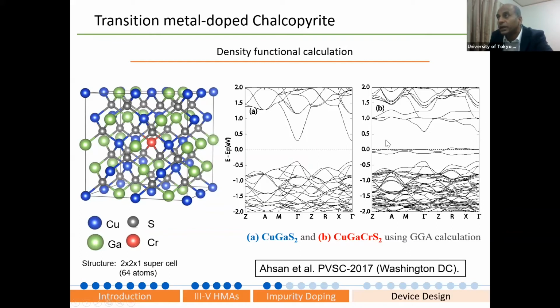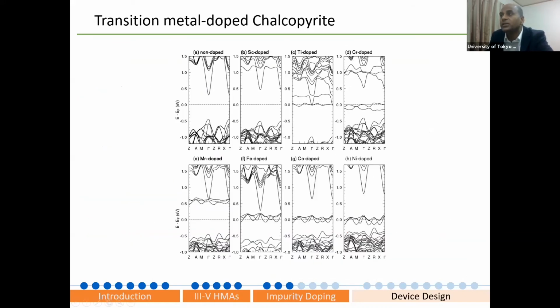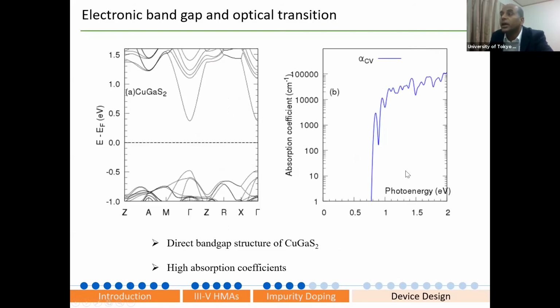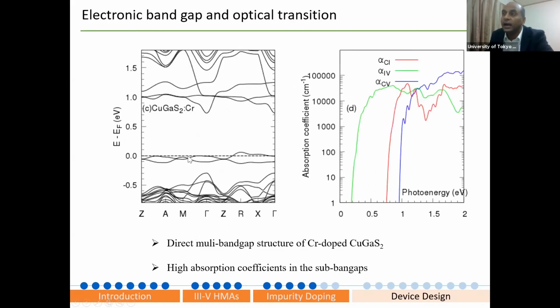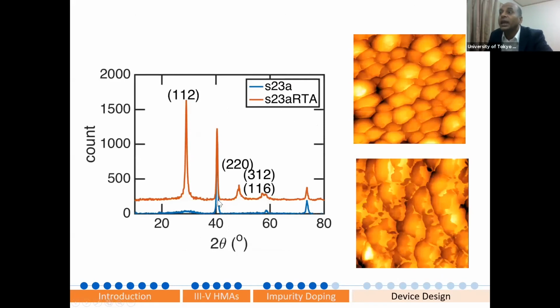Here you see you have one band gap. Now here you have three band gaps at the gamma point. Okay. And I have presented this in the photovoltaic conference in Washington, D.C. 3 years back. And since then, we started a lot of calculations, a lot of materials based on DFT, and we are tuning different material systems. And this is a calculation that if you have a single band gap, you see a single absorption coefficient. But if you have an intermediate band gap, in principle, you have three band gaps and three different absorption coefficients. This is based on DFT calculation, not experiment, because experiment with this kind of material is very, very challenging.